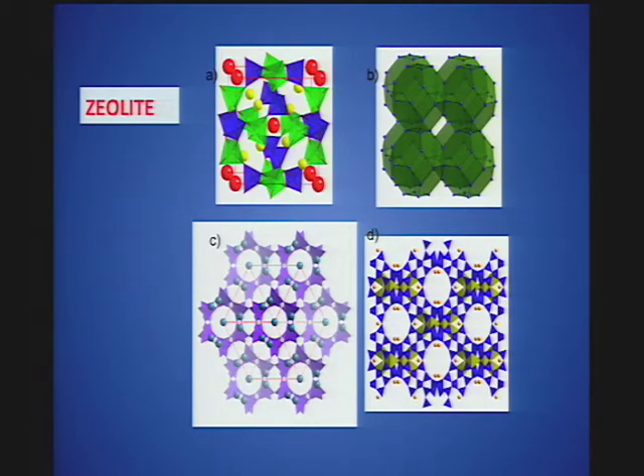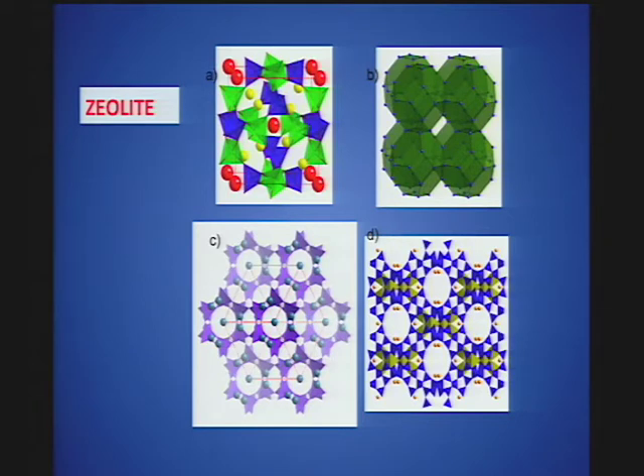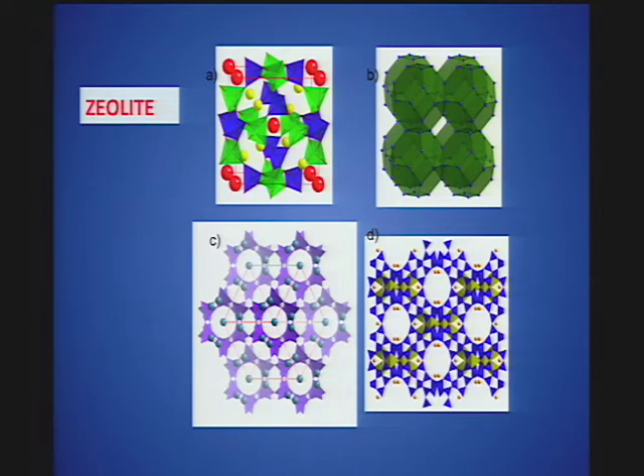Basically there are two types of regions: there are the regions where the atoms are closely bonded, and there are the regions between those closely bonded regions that can, in some cases, be twenty percent, a hundred percent, a thousand percent of the volume of the dense packed materials. In the last decade, a series of materials that build upon similar principles — but containing both inorganic and organic building blocks — have been developed. These are generally called metal-organic framework materials, or hybrid materials. Whereas the zeolites are largely inorganic, the hybrid materials are a mixture, and what that lets you do is create a greater variety and a greater porosity.